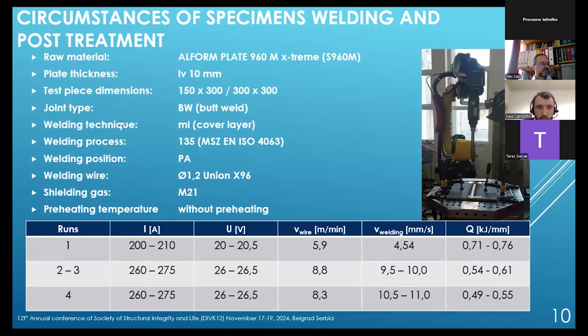Based on this, we started to prepare the weld specimens, made from Alform 960 thermomechanically rolled high-strength steel material in 10 millimeter thickness plates. You can see the setup here. What is important is that during the welding we try to simulate a rigid structure. Therefore, we fix the plates to avoid free deformation. That also has influence on the residual stresses.